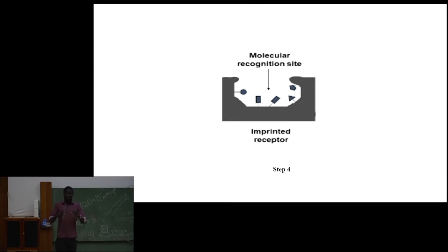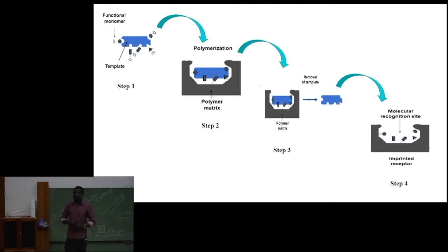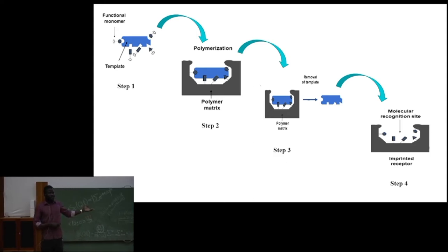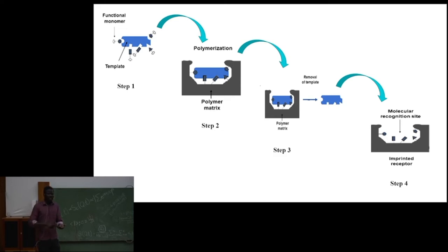This is important because the whole process takes about four days. To give you an alternative, synthesizing antibodies will take about six months. We do this in only four days. And with these four days, we have not just a perfect binding site of the protein template we are imprinting, but we also have additional characteristics. For example, proteins are sensitive to temperature or pH, but this imprinted structure can be used at any temperature — it's irrespective of the chemical in the surrounding vicinity. It's also robust, has a long storage life. These are the additional characteristics we are interested in.